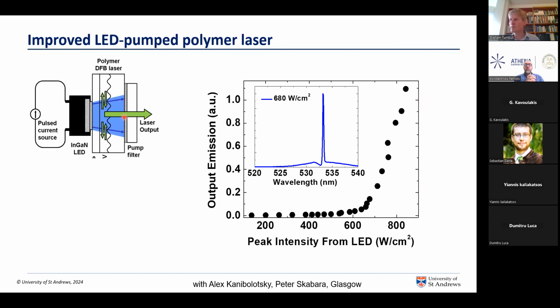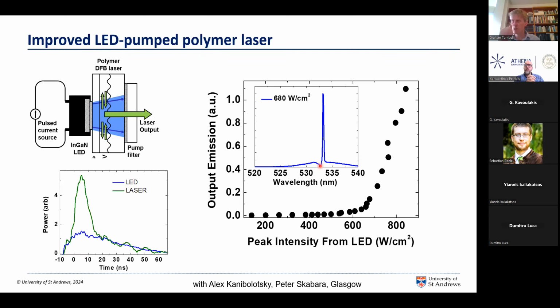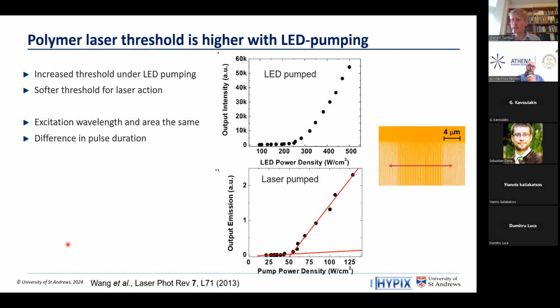So this shows the typical characteristics, where now we have a few hundred watts per square centimeter threshold. So this has gone up from the low values that I just previously mentioned, but we get a nice single frequency laser emission. And we can see temporally that when we drive the laser, this shows the pulse of the light emitting diode, and this shows the laser pulse that switches on a little while after the light emitting diode has started pumping the device. Now, the reason that these thresholds are higher, we had to think about a little bit, because if we compare the same laser device pumped by either an LED or by a laser of the same wavelength and same excitation area, we find that the laser-driven organic semiconductor laser has a threshold that's about a fifth of the LED pump structure.